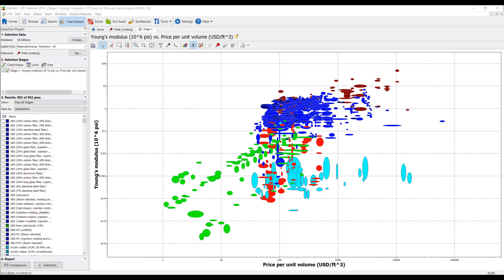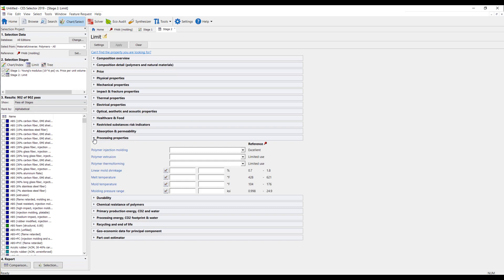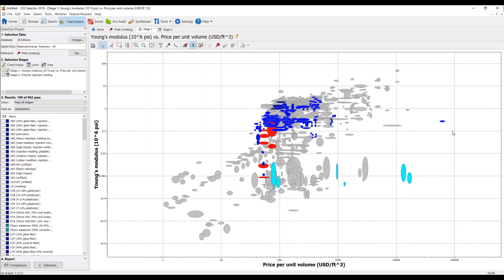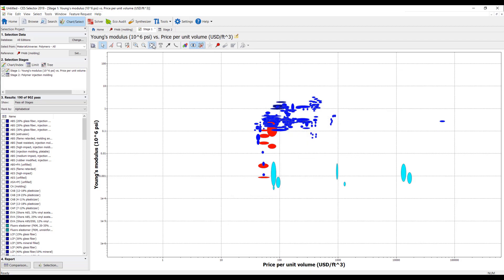I want to filter these materials in order to find suitable replacements for my particular application. First, I'm going to eliminate all polymers that cannot be used in an injection molding process. To do this, I'm going to create a limit, and under Processing Properties, I'm going to set Polymer Injection Molding to Excellent. I'm going to apply this limit and then go back to my tree. Everything that is grayed out is not able to be used in an injection molding process, and we have gone from 902 possible materials to 190. I'm going to remove all those failed materials and then resize my graph.